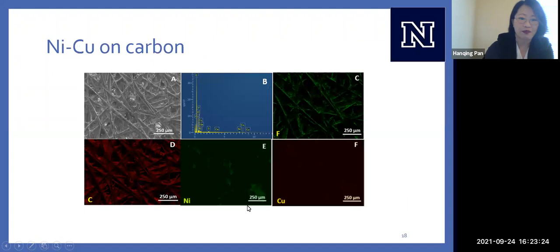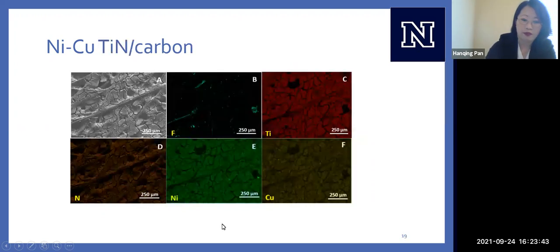So we can also confirm what's on our catalyst with elemental analysis. So this is nickel copper only on carbon. And so they are depositing only along the spindles and fibers of the carbon, and it's not uniform. But when we put down a bed of titanium nitride, our nickel copper deposition is so much more uniform. And so this is partly why it's helping our catalytic efficiency.